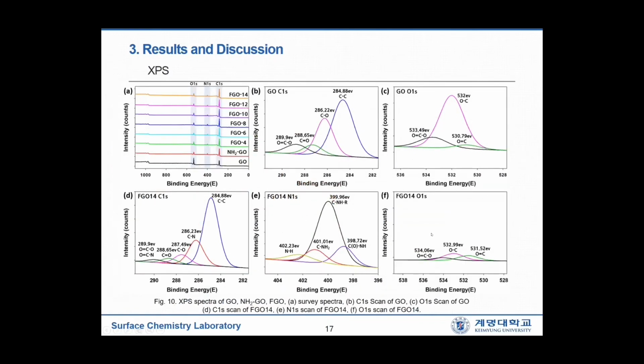This is a series of XPS spectra taken for graphene oxide and functionalized graphene oxide samples. In this survey spectra for the samples, the oxygen 1s peak appears at 532 electron volts, and the C1s peak appears at 285 electron volts in GO samples, but the intensities of these peaks are much decreased in FGO samples, and also